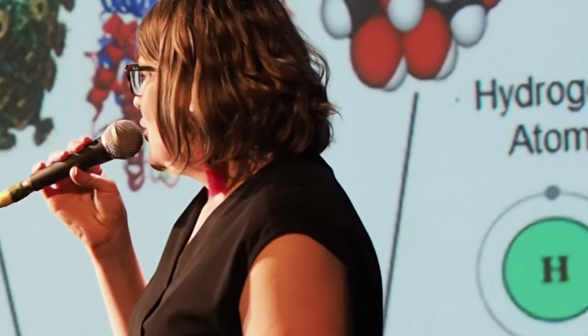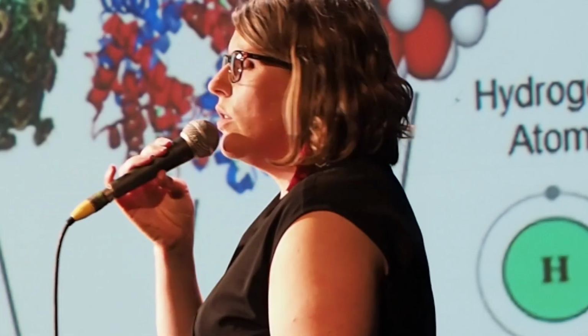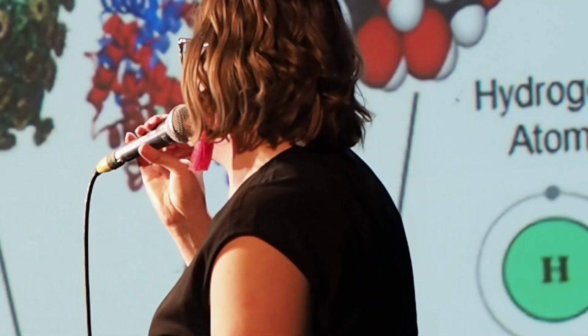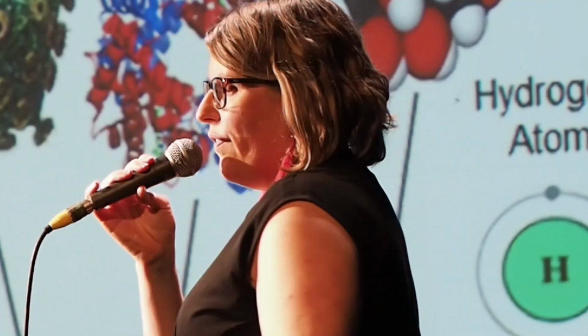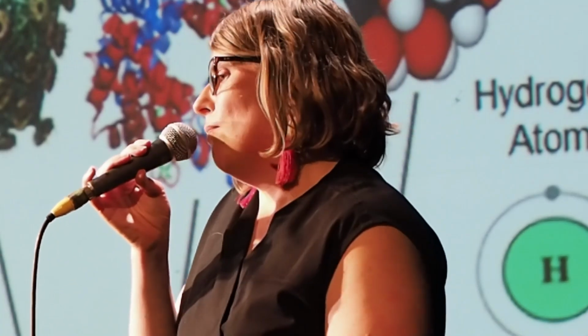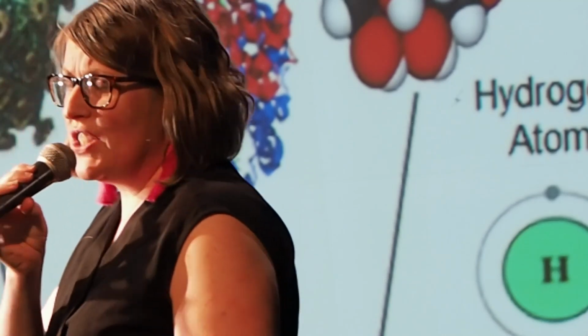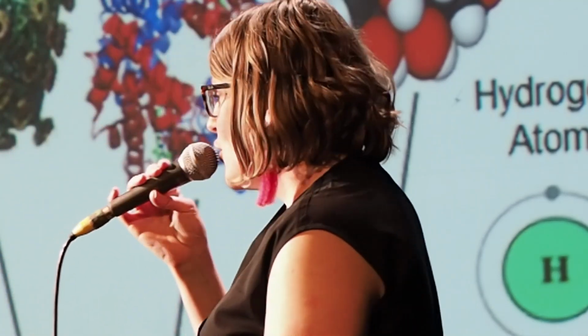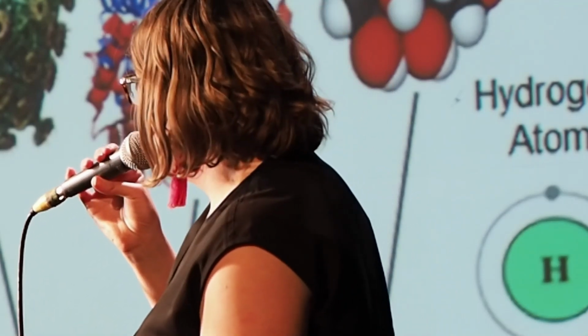So a lot of the films I deposit are 5, 20, 100, 200 nanometres. And you would think, well, surely if 100 nanometres is good, then 10 microns is even better. Like, how is more not better? Well, with these sort of films, we actually don't need more, because most of the things that interact with our thin films, they don't see any more than a few nanometres. So if we show one of our plasma polymer films to a bacteria, the bacteria doesn't see the microns underneath, so we typically only tend to work in that 100 plus or minus range.